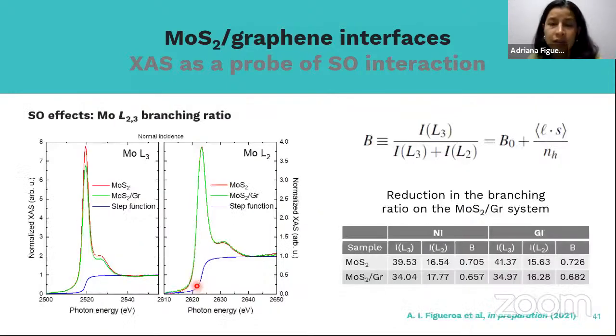And then finally, we also measured at the molybdenum edges, at the molybdenum energies, in order to extract the values of the branching ratio in the MoS2-graphene system, compared to the system without graphene.